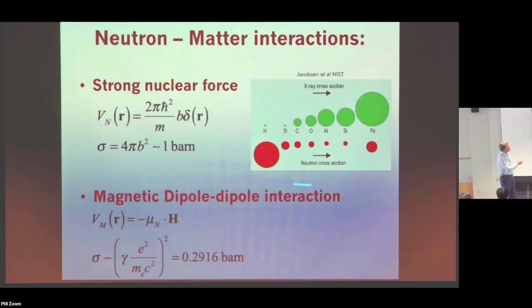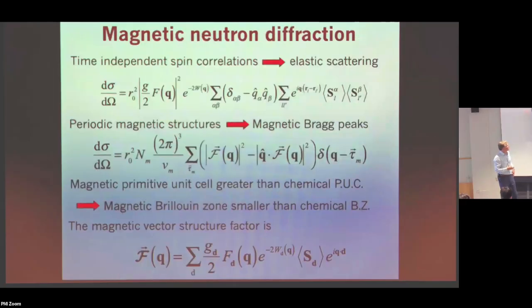A little later in the talk, I will emphasize the beneficial aspect of this nuclear interaction as compared to X-rays. With X-rays, it's just the charge density that determines the strength of the Thomson scattering. But for neutrons, it actually varies by isotope and by element. And so we can be very sensitive to hydrogen inside a material that has lead in it. With X-rays, we would just see the lead, but with neutrons, we see both the hydrogen and the lead. So very often there are benefits in the structural determination with neutrons when we have light elements in the presence of heavy elements.